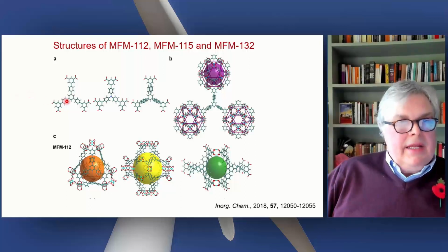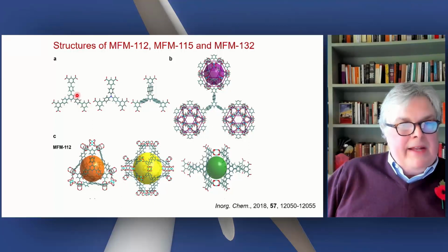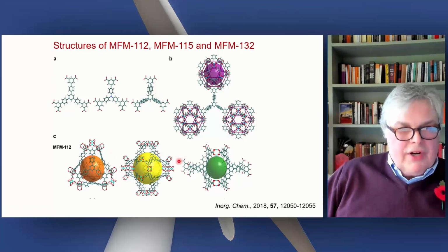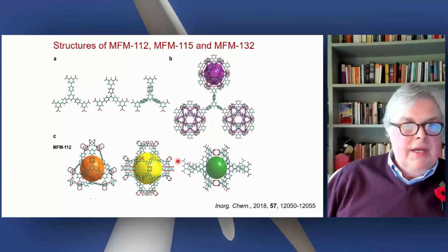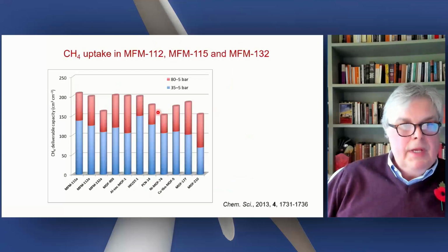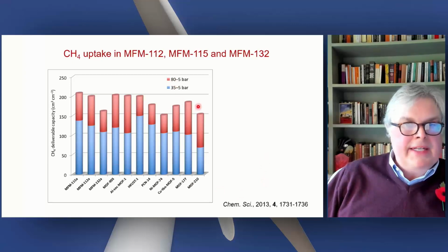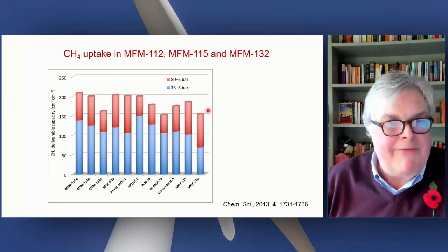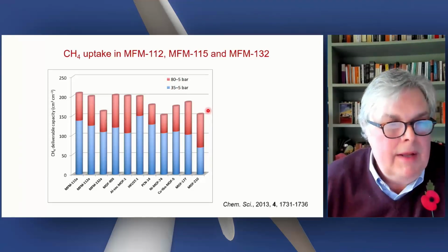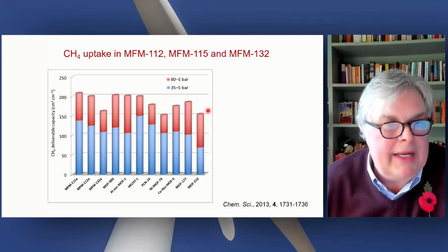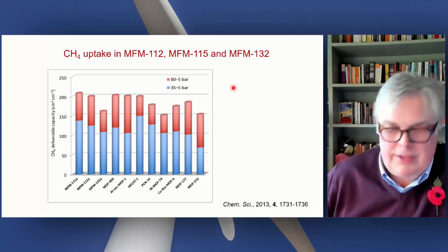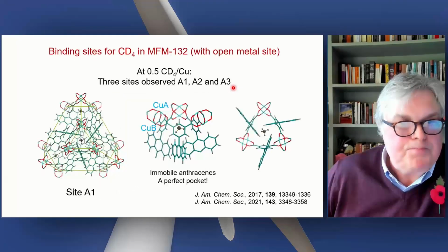And so this is again a series of MOFs. You've taken a phenyl group, replaced it by a nitrogen group, reintroduced the phenyl group, but put anthracene groups in here. And you form isostructural arrays of materials, but with different ligand centers, and look at the methane uptake as a function of ligand, as a function of pore size, and then determine the capacity between 35 and 5 bar, which is the deliverable capacity of any system, because you don't really want to go in a pressure swing system below around 5 bar, because then you need to actually go to a vacuum.